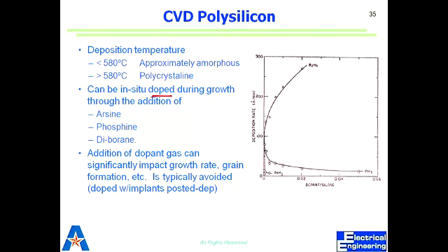Depending on how much dopant we have with respect to silane, our deposition rate changes. Because you're adding those gases, it can change the growth rate and the grain formation during the deposition. So we can do that, or we can do implantation afterwards to dope it. This shows how it behaves for phosphine. As you increase the phosphine, your deposition rate goes down. But if you use diborane, your growth rate goes really high. So it can grow really fast. What's happening is they have impact on different parts of the grains.